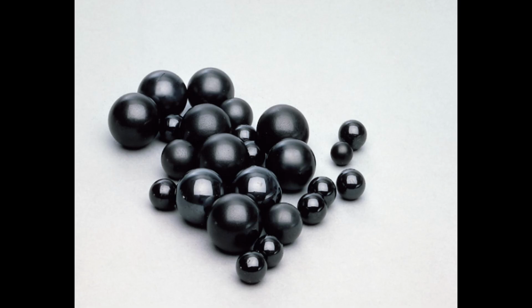It's predominantly argon, but there are some materials that are HIPed in nitrogen, such as silicon nitride, as an example, ball bearings for electrical vehicles. These are HIPed in nitrogen. And then because nitrogen and molybdenum like each other a little bit too much, usually graphite units are used for those graphite furnaces in order to use the nitrogen atmosphere. Yeah, good idea too. But it's mostly argon. Most of the components out there in the world are HIPed in argon.